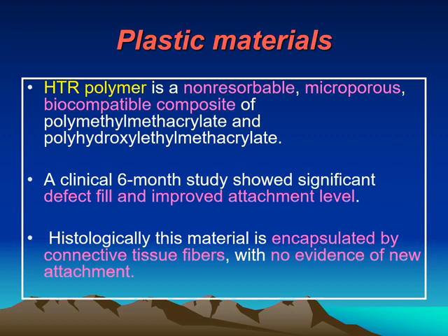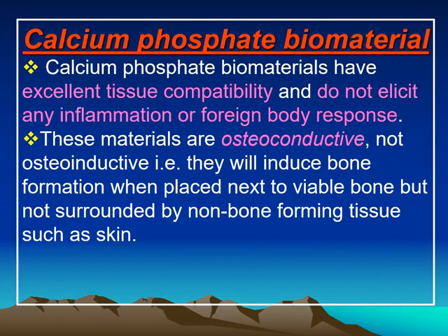HTR polymer is a non-resorbable, microporous, biocompatible composite of polymethyl methacrylate and polyhydroxyethylmethacrylate. A clinical 6-month study showed significant defect fill and improved attachment level. Histologically, this material is encapsulated by connective tissue fibers with no evidence of new bone formation.